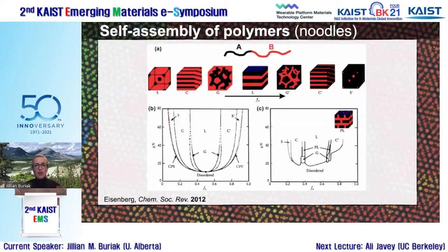And so the idea, which I know because KAIST is a real powerhouse in this area, I know you know this very well. The idea is using soft noodles basically that will self-assemble spontaneously under the right conditions. So if you have one block copolymer with a chemical composition A that's holding hands covalently with another polymer, chemical composition B here, and depending on the ratio of the sizes of these two blocks with each other and the chemical conditions, you can then access a broad range of different self-assembled morphologies, all the way from this, for instance, this body-centered cube to this hexagonal cylinders to these intricate gyroidal structures, these lamellar type phases, and then the inverse.